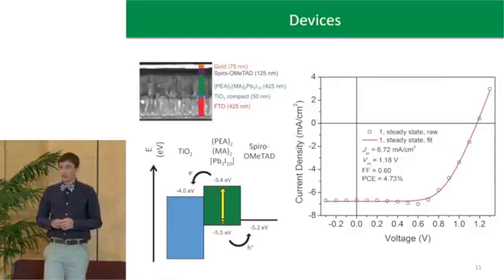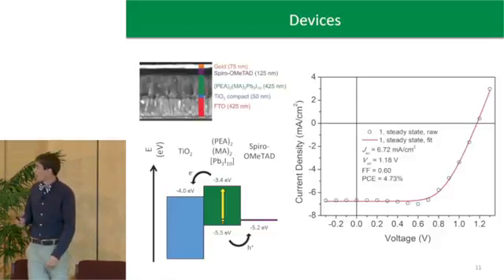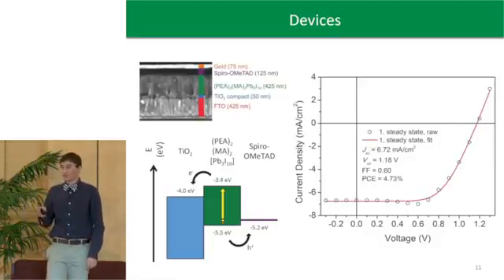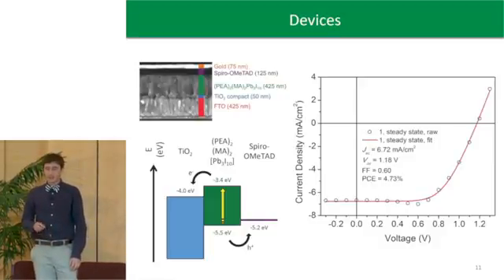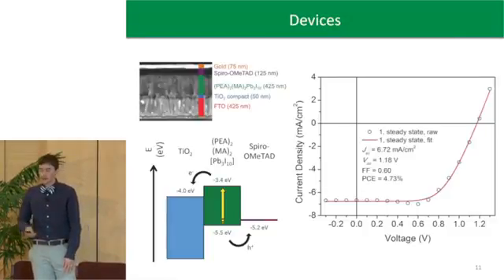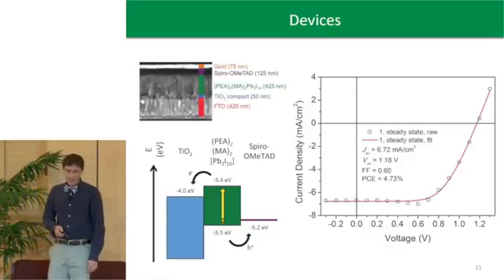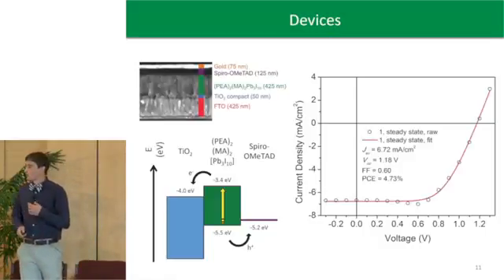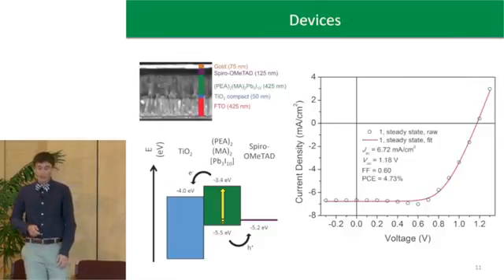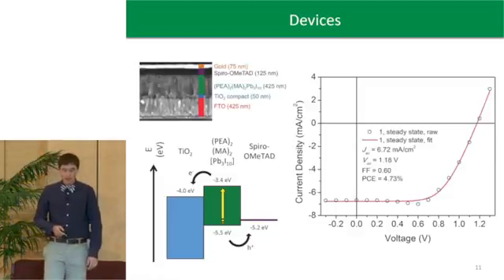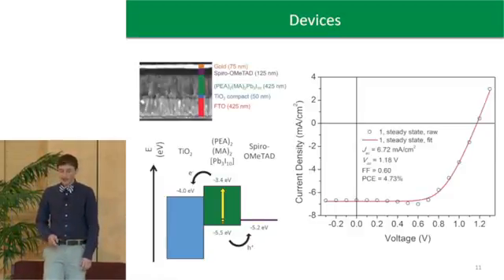We're getting a pretty good JSC. JSC is the short circuit current, which is at the y-axis. This is essentially a measure of the photocurrent in the device. It's certainly limited when you compare it to the 3D perovskite, but we think it's very good for a first try. And we think that increasing that short circuit current, or the photocurrent, will allow for better devices in the future. Because of that slightly smaller photocurrent, we are getting an efficiency that's lower than 3D perovskites, just under 5% at around 4.73. But we hope in future generations we can improve that.